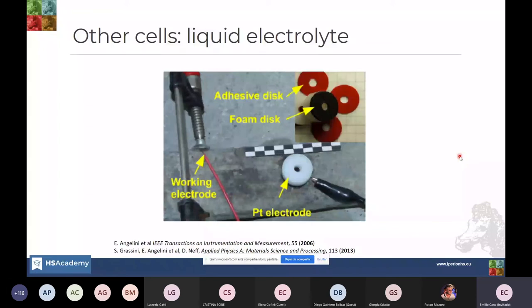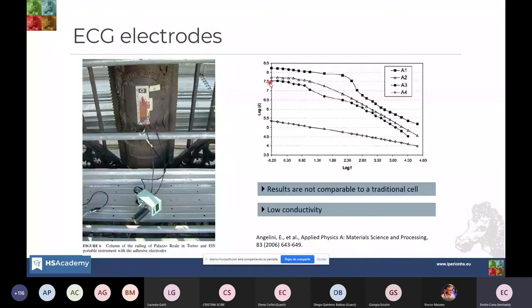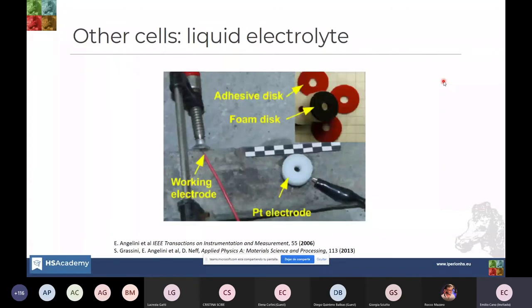One of them was the use of adhesive foam discs to attach a small container to the surface, in which they put the electrolyte, using a platinum electrode as counter electrode. Using this system, they have measured, for instance, the impedance in the railings of Palazzo Reale di Torino. They used this system with a liquid electrolyte.